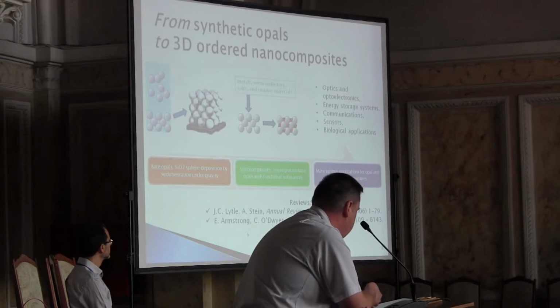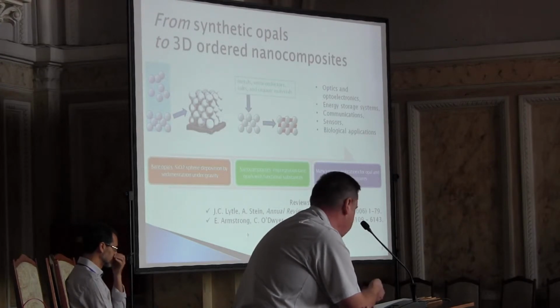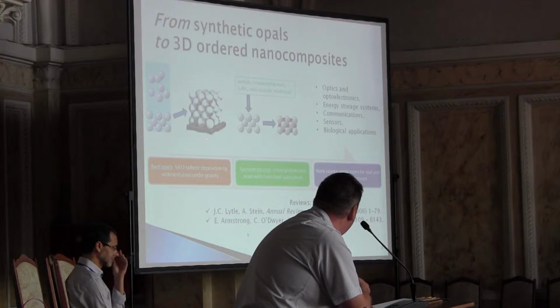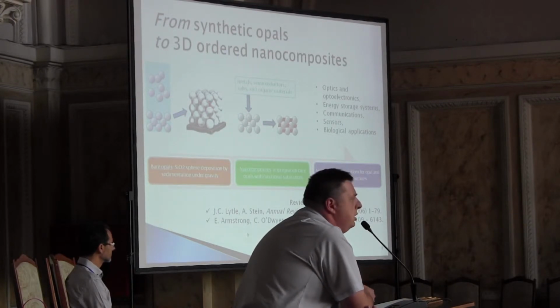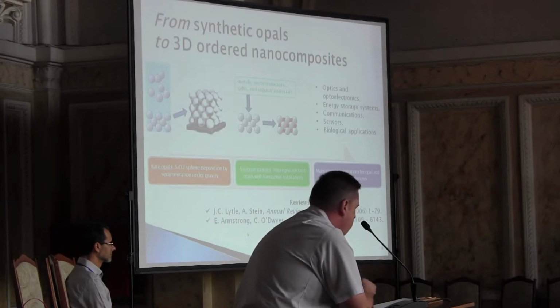The characteristic size of the globules in our experiments is 300 nanometers, and the linear size of the channels of pores is no more than 100 nanometers.